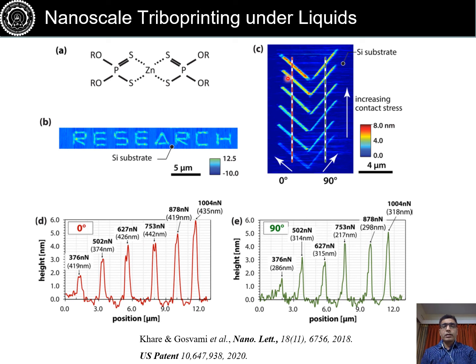so we get thicker pattern, whereas the thickness or width of the pattern does not change that much, only a few percent, whereas height of the pattern changes by factor of 3 by varying the load by factor of 3. And of course we see some asymmetry in the pattern as we slide at different angles because of the asymmetry of the contact itself. So that also matters. If the contact is symmetric, you will get symmetric pattern, otherwise the contact shape will also affect the size and shape of the pattern.